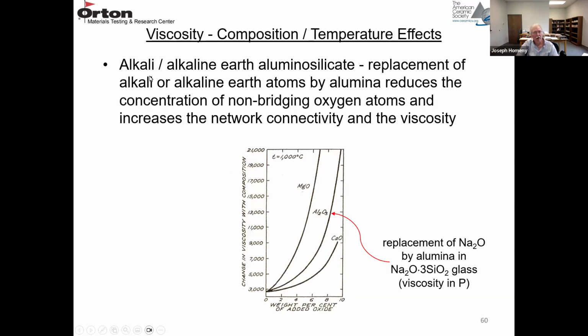And I think this is the last slide. The replacement of alkali or alkaline earth atoms by alumina reduces the concentration of non-bridging oxygen atoms and increases the network connectivity. So for the previous cases of MgO and CaO, the +2 charges increase the bond strength and increase the viscosity. But now the addition of Al2O3 replacing Na2O is making the non-bridging oxygen atom concentration decrease, creating more bridging oxygen. So it's going to see an increase in viscosity.